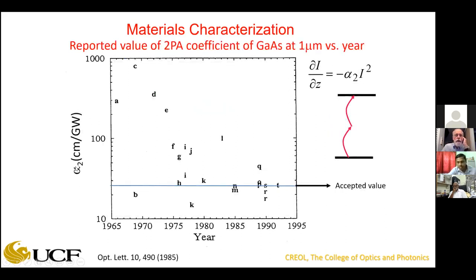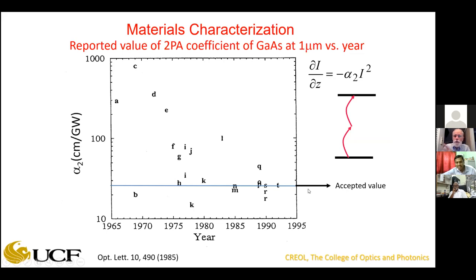Here's my favorite viewgraph: the two-photon absorption coefficient in units of centimeters per gigawatt as a function of the year published in the literature — on a semi-logarithmic scale. Notice this is for a single material, gallium arsenide, at a single wavelength of one micron. Notice how the values slowly decrease over time, converging to the accepted value in the 1990s of around 26 centimeters per gigawatt.